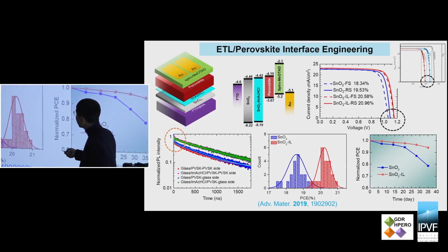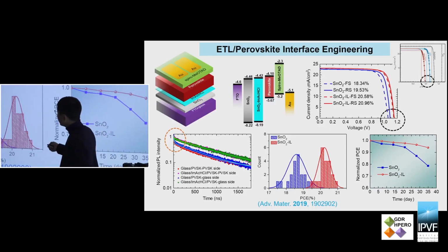Usually the FTO conducting glass, you put the tin oxide or TiO2, whatever. Tin oxide is probably better than TiO2 because of some UV stability. And then you probably deposit the perovskite on tin oxide, the ETL, and then the HTL material, and then the electrode on the top.